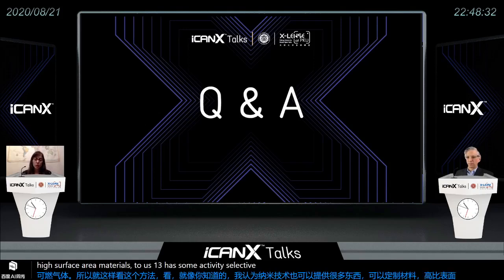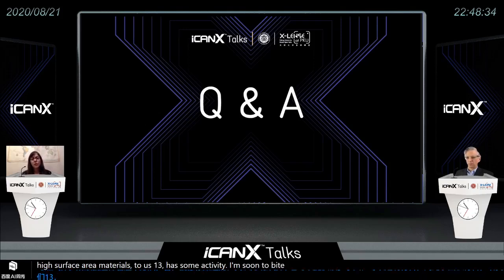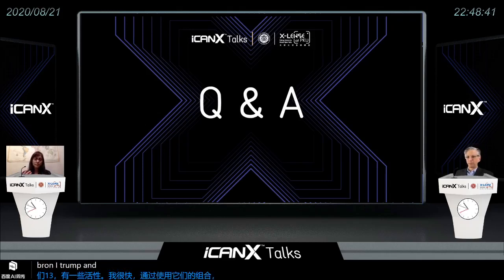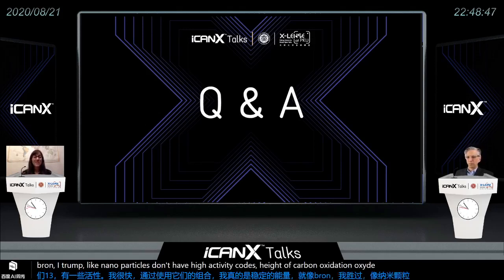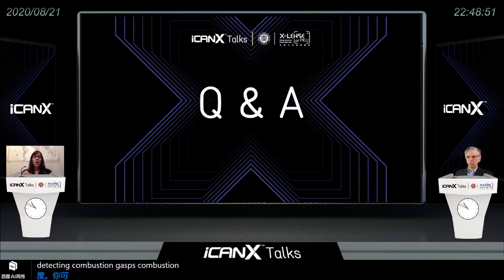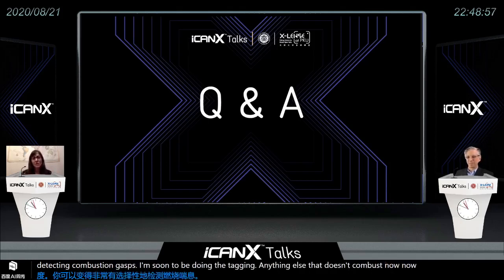So by using this combination of thermally stable aerogel-like boron nitride and the platinum nanoparticles that have high activity towards hydrocarbon oxidation, we can become very selective to detecting combustible gases. So we don't detect anything else that doesn't combust. Now, of course, there are many things that combust.